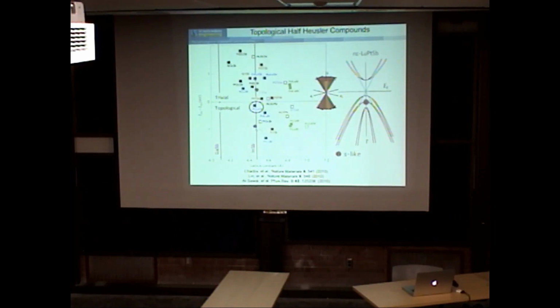Unfortunately, I don't have it here. In the bulk, it's a zero gap semiconductor, unstrained, or it's a semi-metal. Theory suggests if we can strain it, we can open up a gap. And that's something we're going to try and do. First, we try just growing it to see if we can grow it as good as possible and not worry whether or not we have bulk conduction.